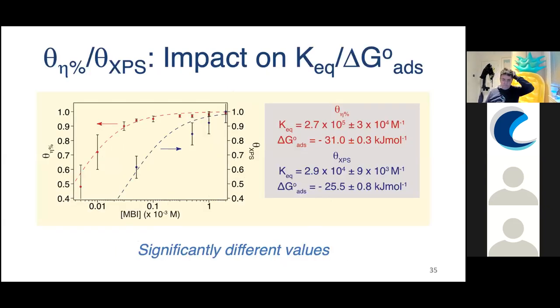So let's have a look at that. On this, it's the same data. What I'm plotting here now are the fits using the Langmuir isotherm to both the efficiency theta and also the XPS theta coverage. And here are the numbers we get out, the K equilibrium and the delta G. You can see the K equilibrium is an order of magnitude higher essentially than for XPS. So the one for efficiency, the equilibrium constant, is an order of magnitude higher. And you also get a significantly lower delta G, so minus 31 compared to minus 25.5, and well outside the errors. So these numbers are significantly different.